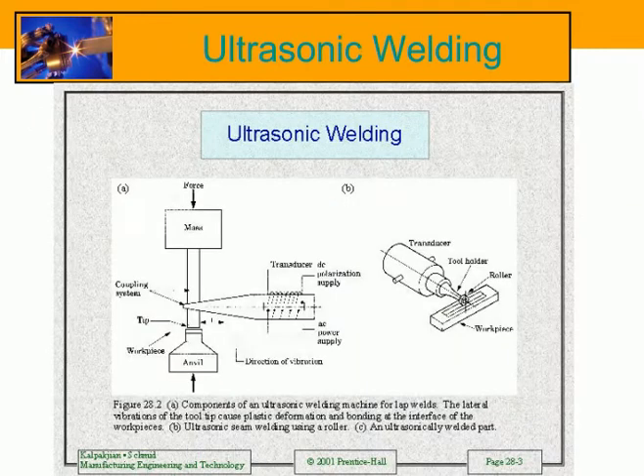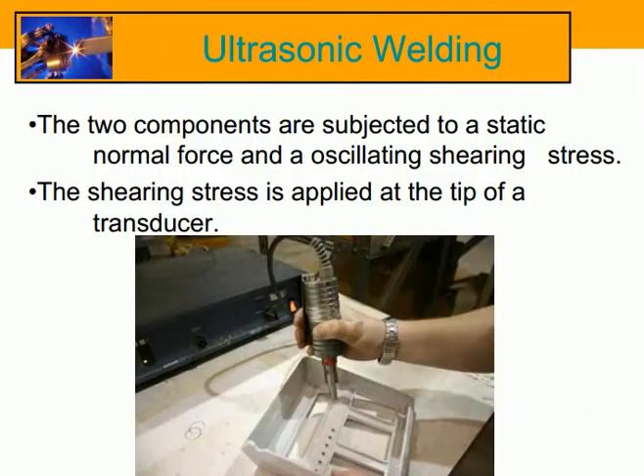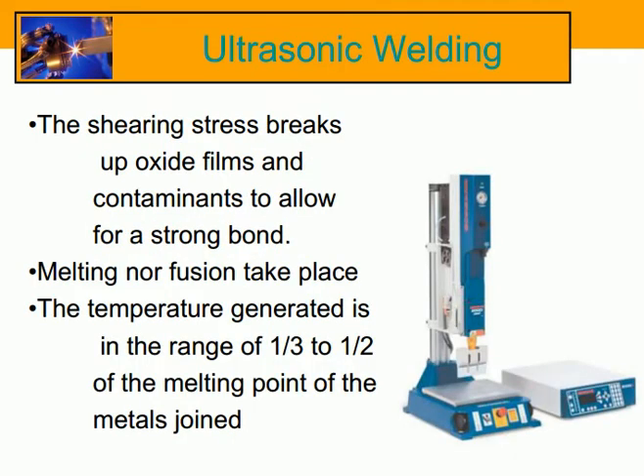Ultrasonic welding: the two components are subjected to a static normal force and an oscillating shearing stress. The shearing stress is applied at the tip of a transducer, breaking up oxide films and contaminants to allow for a strong bond.